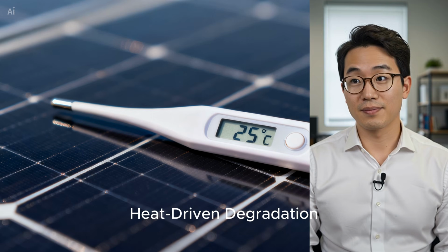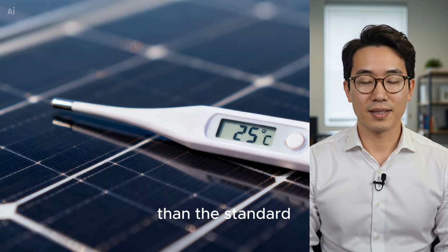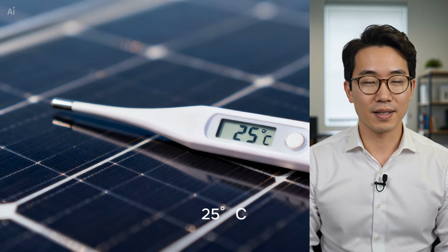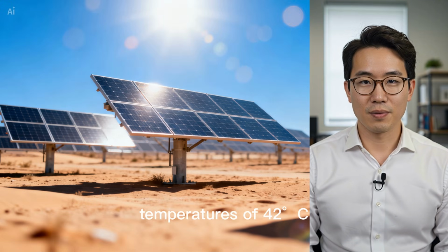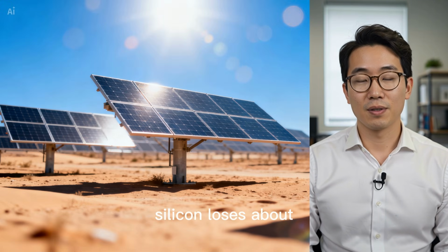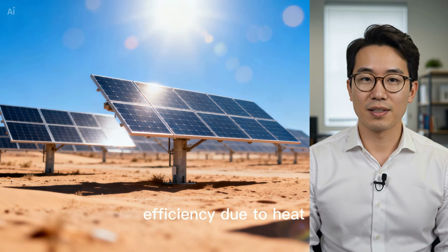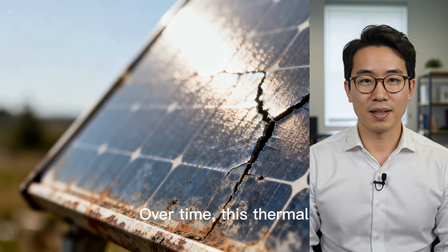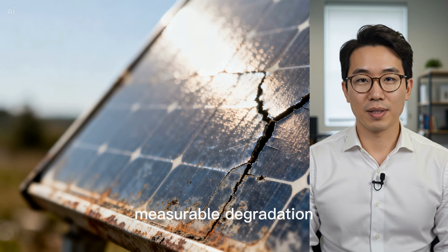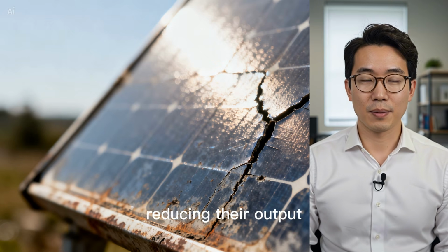Heat-driven degradation. Solar panels operate much hotter than the standard testing temperature of 25 degrees Celsius. At typical operating temperatures of 42 degrees Celsius, silicon loses about 6 to 8% of its efficiency due to heat. Over time, this thermal stress can result in measurable degradation of the panels, reducing their output.